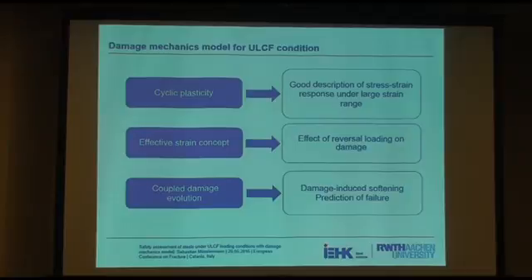Okay, the model itself shall be able to consider the effect of cyclic plasticity in order to have a good description of the stress-strain response under large strain amplitudes, or the cyclic loads with large strain amplitudes, because we want to make use of a strain-based model, so we need to be sure that our calculated strains are really correct. For the effective strain concept, we need to consider the effect of reversal loading on damage, because not every equivalent plastic strain will really contribute to ductile damage. So we need to make sure, or we need to invent, an effective strain concept. And of course, we also want to take into consideration that damage will induce some softening of the